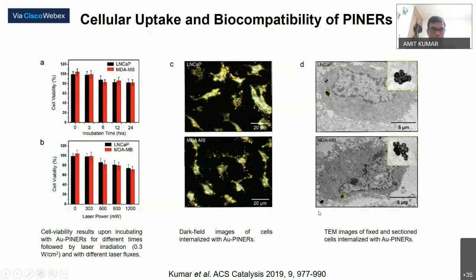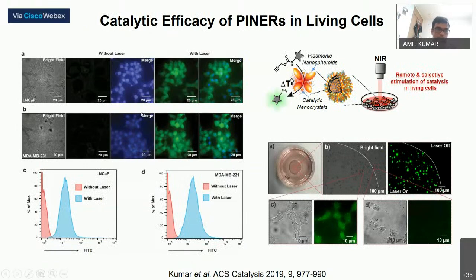So after feeding the cells with the nanoreactors, PINERs, we shine the laser. We feed the reactant, which is protected rhodamine 110, for 5 to 6 hours, and then we wash away the extra nanoparticles and also extra fluorophore. And then we shine the laser for some time, and we see that after laser irradiation, we clearly see the green fluorescence emerging from the cells, which is due to the synthesis of free fluorophore from the protected fluorophore. And without laser, there is no emergence of such green fluorescence, which clearly tells that the intracellular reaction can only take place in the presence of laser.